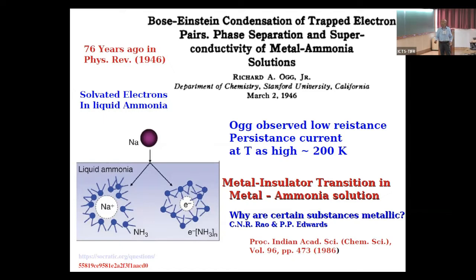can undergo Bose condensation. He envisaged that possibility because what he did was he took liquid ammonia, and sodium or lithium or these alkali metals very easily dissolve in it. And once it gets dissolved, the electron gets liberated, then you cool it down, it becomes a crystal or a solid, an amorphous solid, where what happens to the free electrons, that's what we will see. And Ogg claimed that he saw persistent current lasting for a few minutes at temperatures as high as 200 Kelvin. He also saw it once in 30 samples, not always reproducible.